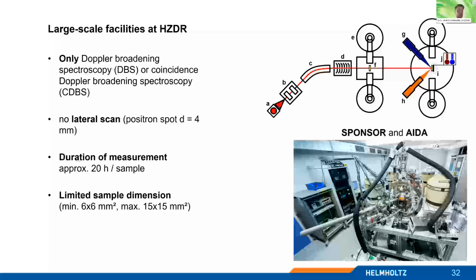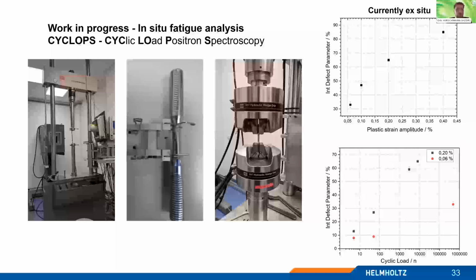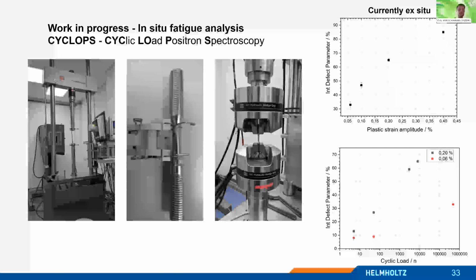At the end, coming to a little outlook for our work in progress, which is our in situ fatigue analysis. As I said before, we have these measurements for the stress strain or cyclic load measurements, which were done ex situ, but we plan to do this within the next 2 to 3 years in situ with a special cyclic load machine, appending it with the positron lifetime, and have these curves on one and the same sample without cutting it into pieces. And this brings me to the end.